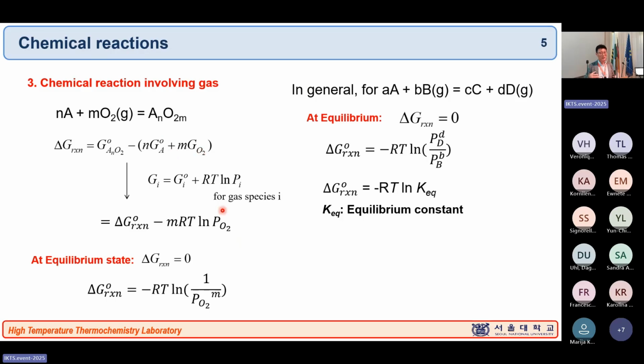And gas can easily make a gas solution phase. For example, oxygen with nitrogen as air, okay? Of course, you can make pure oxygen, but depending on the total pressure, your Gibbs energy can be changed. The Gibbs energy of the pure oxygen at standard state means at the 1 atm condition. But if you make it 100 atm, its Gibbs energy is changing from the 1 atm condition.